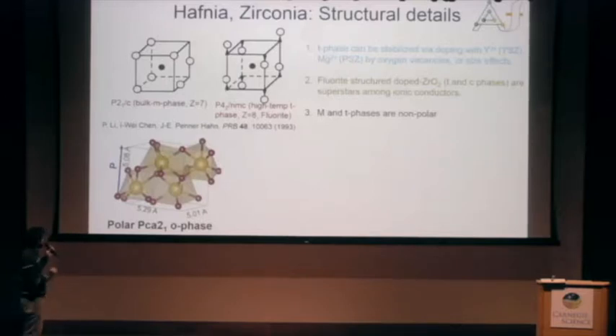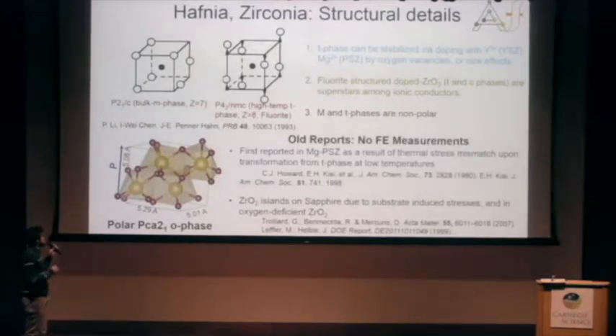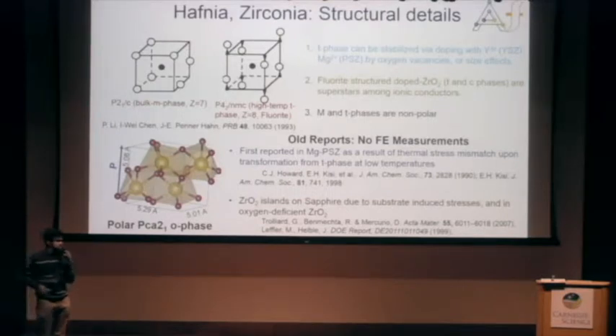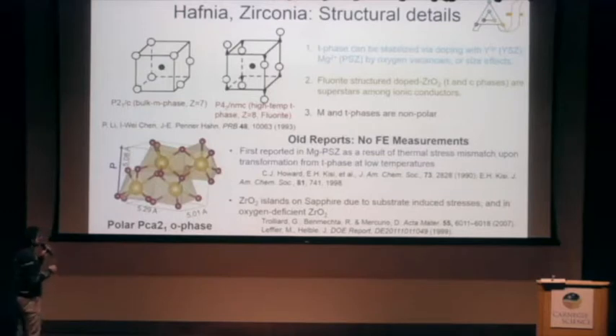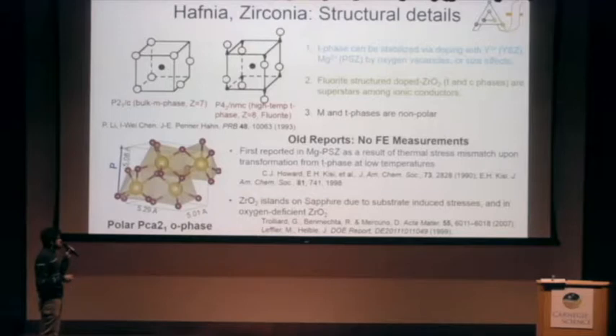The saving grace is the existence of an orthorhombic phase. And this is what is reported to be ferroelectric, or what is assumed to be ferroelectric in most of the recent works on hafnia-based ferroelectricity. This phase was first reported in the 1990s in zirconia as a bridge phase between the M and the T phases during the phase transformation, but there were no ferroelectric measurements until 2011.